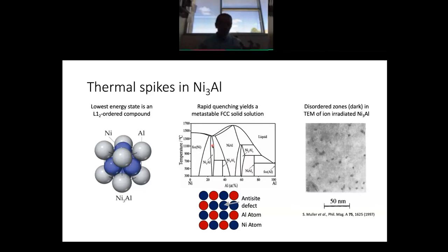Anything that's between the perfectly ordered and the perfectly disordered state can be described as a nickel-3 aluminum lattice containing a certain number of anti-site defects. So an anti-site defect is basically a location where you were expecting to have an aluminum atom, but you have a nickel atom instead. Or you were expecting to have a nickel atom, but you have an aluminum atom instead. Okay?